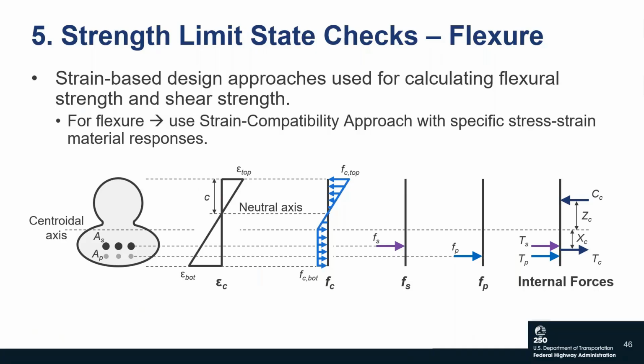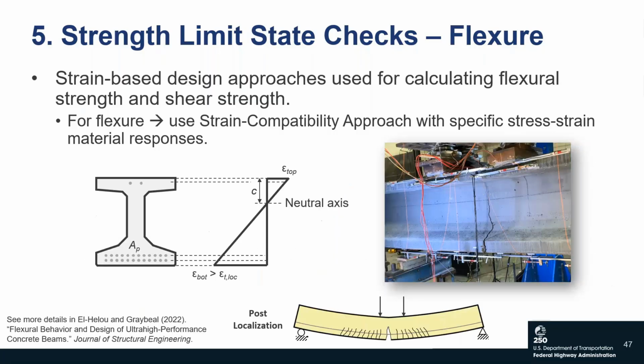Using strain compatibility allows us to take advantage of the tensile properties of the UHPC, and it also allows us to capture different failure mechanisms that may occur in the member. So with UHPC flexural members, they're generally going to fail because we exceed the tensile capacity of the UHPC. So we can capture that using strain compatibility. But we can also capture if concrete crushing controls or if the rupture of our reinforcement controls. So strain compatibility is a really versatile analysis approach.